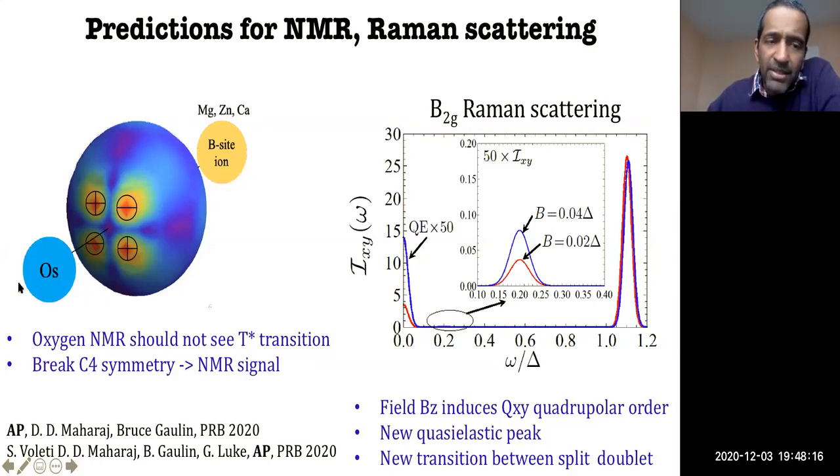And it turns out in the cubic system, the oxygen sits on this line here that's connecting these two. Okay. And what that implies in this cubic system is that if I have octopolar order, then on this oxygen, the magnetic field satisfies the property that if I do a C4 rotation around this axis, then I interchange the minus and the plus. Okay, these go into each other.